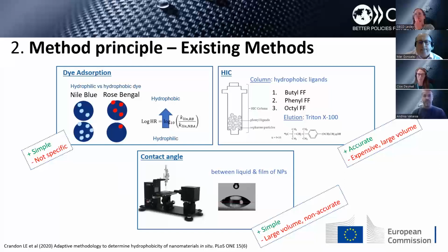The first method is the dye adsorption method, in which you label the nanomaterials using a hydrophilic and a hydrophobic dye. Nile blue is the hydrophilic, rose bengal is the hydrophobic, and by measuring the ratio of the number of molecules adsorbed on the particles, you have a direct measurement of the hydrophobicity. So if the particle adsorbs more rose bengal than nile blue, it is tendentially hydrophobic. This method is relatively simple, but as we will also show at the end of the presentation, I think Chloe will show it, it is not really specific because these chemicals bind in a very non-specific way to all the particles. So they cannot distinguish between different degrees of hydrophilicity or hydrophobicity.